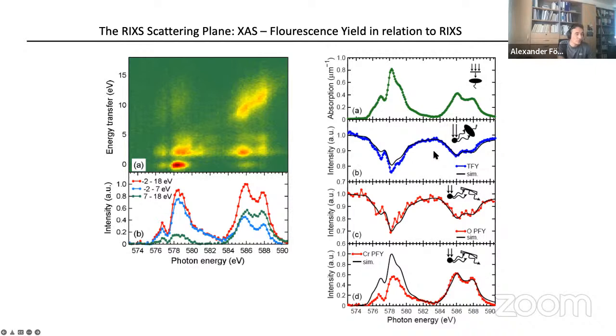which we call self-absorption. Basically, what happens is the light going in is absorbed in a thin layer, and the light coming out is coming from a deep layer. And that's why you don't really measure the absorption in terms of what we want in Lambert-Beer's law. But in a way, you measure the variation of the depth of field, how deep the radiation penetrates the material. This is done no matter if you do total fluorescence yield or partial fluorescence yield. And whenever you do a partial yield measurement where you don't measure perfect transmission, you are always suffering from that, which we have exaggerated massively here.